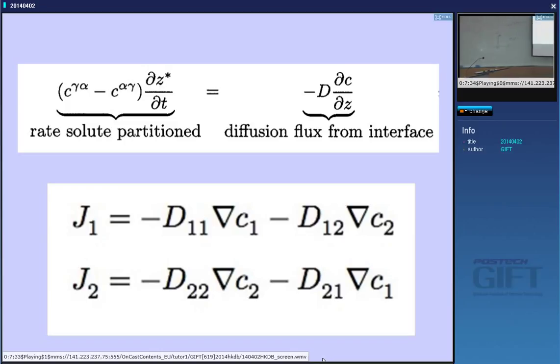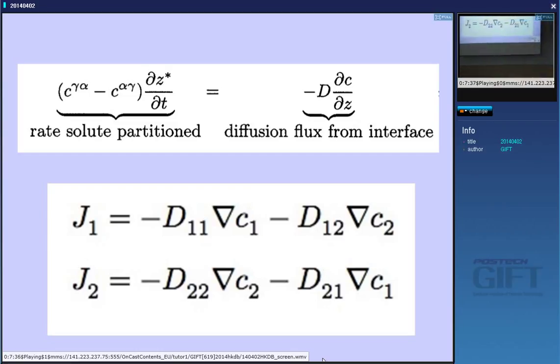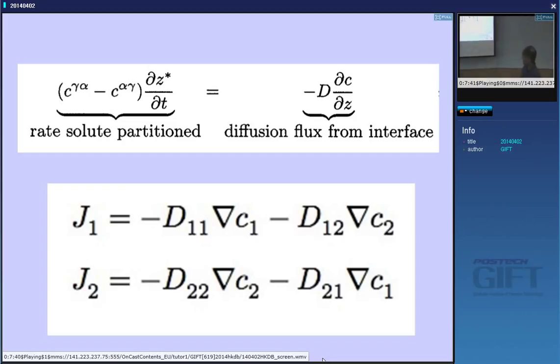You can see how we can satisfy these two equations simultaneously, given that the diffusion coefficient of carbon is eight orders of magnitude greater than that of manganese. If I make either the gradient of carbon flat, or make the gradient of manganese extremely steep — so that the ferrite is growing with the same manganese concentration as the alloy — then the two fluxes can keep pace with the same interface. There is only one interface moving.